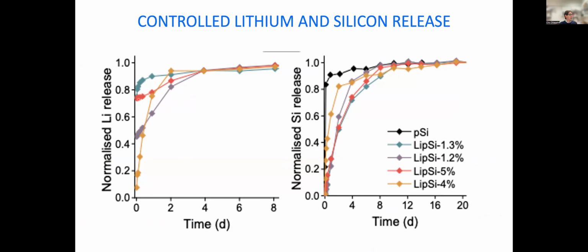And indeed, by changing the parameters of the lithiation, we can control the release profile of the ions, okay? We can either have, for example, for lithium on this side, a burst release where a lot of the lithium is released very early, and then a secondary sustained release, or we can have a more sustained release from the beginning, or we can have intermediate states. And at the same time, for the silicon, we can control the release from either being more rapid or more slow. And if you compare that to the dissolution of the original porosilicon itself, you can see that the introduction of lithium does stabilize the porosilicon matrix in some ways, because even the more quickly degrading one still dissolves more slowly than the original porous silicon.